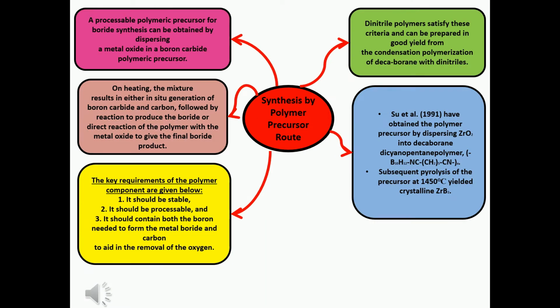Synthesis by polymer precursor route. A processable polymeric precursor for boride synthesis can be obtained by dispersing a metal oxide in a boron carbide polymeric precursor. On heating, the mixture results either in in situ generation of boron carbide and carbon, followed by reaction to produce the boride, or direct reaction of the polymer with the metal oxide to give the final boride product.